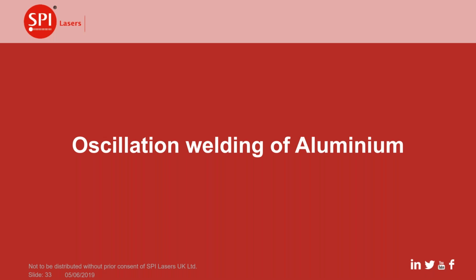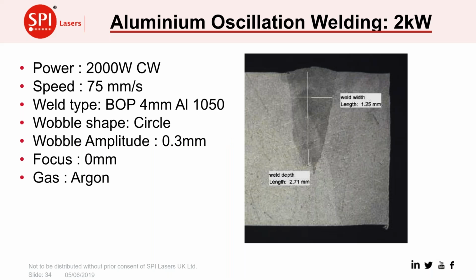So that was copper. The other kind of key material is aluminium, so we want to come on and look at that briefly. Again, we've been concentrating on using a 2 kilowatt fiber laser for these welds. Here we've welded with a circular pattern. This is a 1050 grade aluminium, and with that 2 kilowatt laser at 75 millimeters a second, we've produced a weld that's over 2.5 millimeters deep into the aluminium.